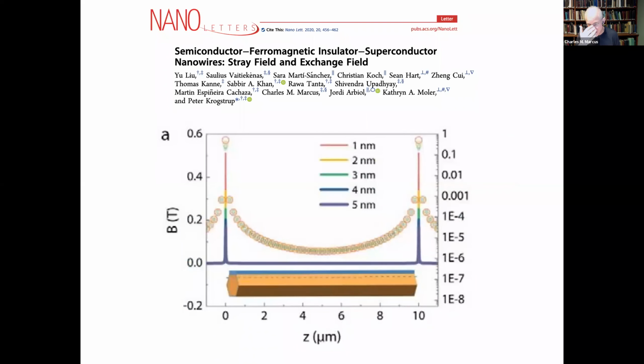There's a simulation of what these magnetic fields are, and they're localized to the ends of the wires. This is the right hand axis, which is a logarithmic scale. So for the moment, let's look at the left axis, which is the linear scale, measuring 1 or 2 or 3 or 4 or 5 nanometers. This gives magnetic fields that are rather significant. Tesla scale magnetic fields, 0.2 up to 0.5 Tesla, depending on where you measure close to the wire, but only at the ends of the wire.